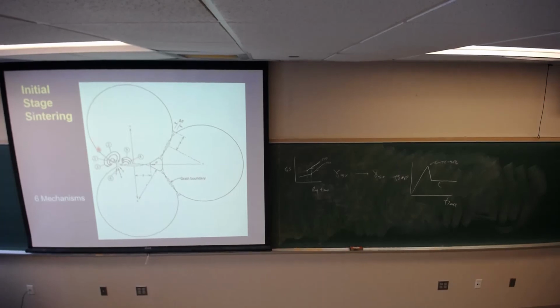So you have curvature here, and you have an inverted curvature here. This becomes a sink for material. So you move material from the bulk or from the exterior to that sink. Then you grow a neck. If you move material from the grain boundary, as shown here for 5 and 4, 4 is grain boundary diffusion, so it diffuses out through the grain boundary to the neck. 5 is bulk diffusion from the grain boundary to the neck.